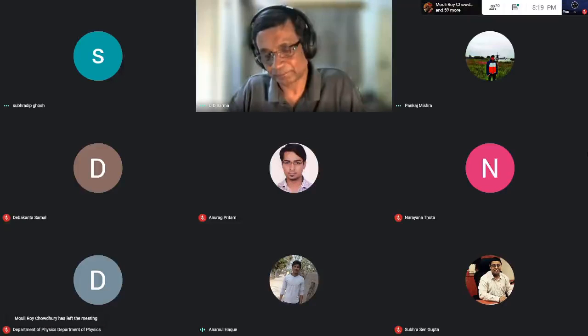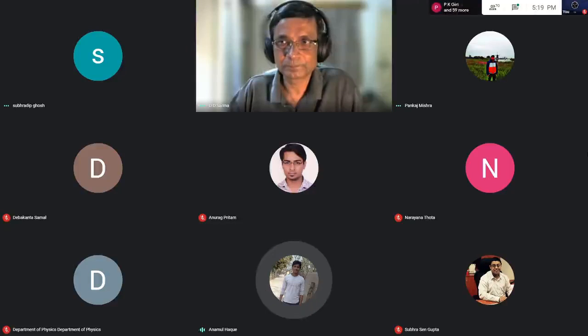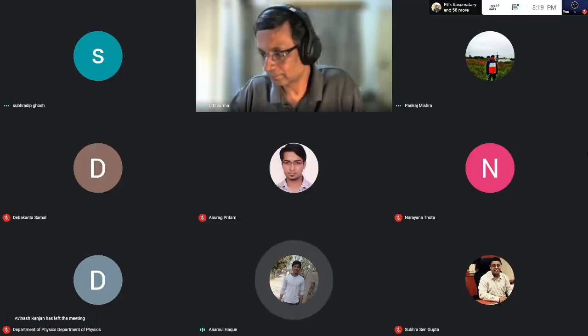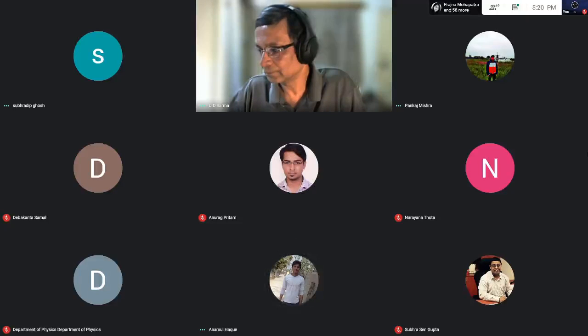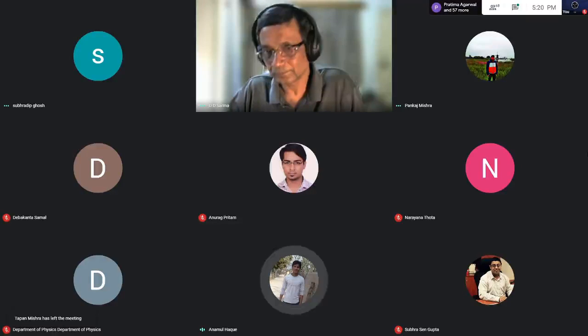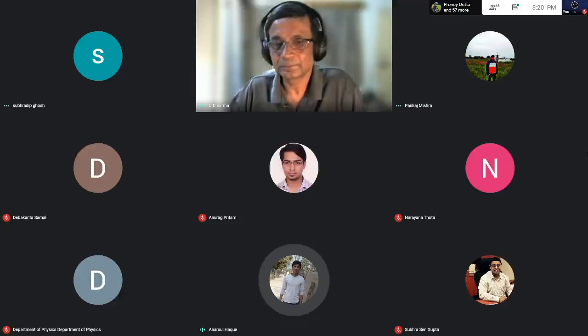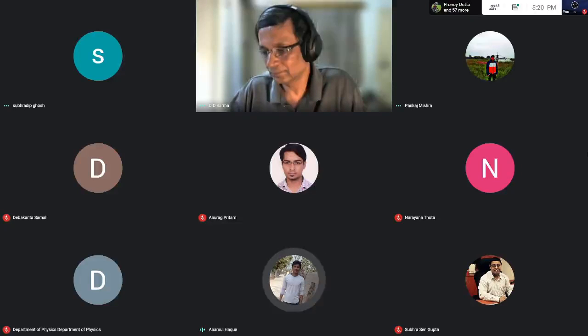The interesting thing I would like to say, sir, is that you have shown that when you replace methyl ammonium by cesium, it is not showing the dielectric constant. But there is a paper that recently came out in JACS 2020. It shows that CsPbBr3 is non-centrosymmetric because the cesium ion is shifted from the center of the perovskite, and they are showing this ferroelectricity, and they have given the evidence for that.